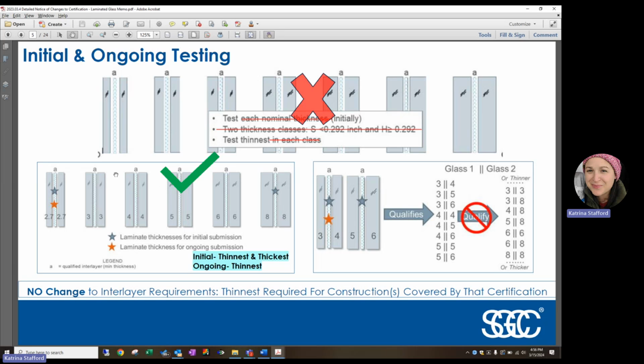And because 2 lights of 8 mil were sent in for testing, you can go thicker. You're certified for that 16 plus, so there's no cap to the thickness of the lights that you wish to use for your configuration. Say a 6 and a 6 millimeter glass with an 030 interlayer, you would not be able to go past that for your thickness of configuration. You'd be capped at the 6 millimeters, but you can make everything in between that and your thinnest.